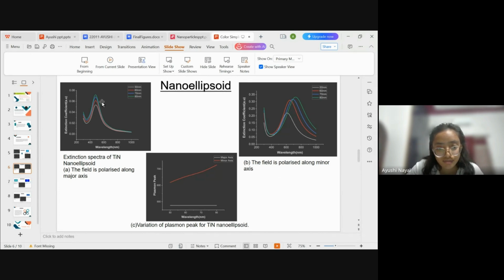The peaks in the graph show the wavelength where the nanoparticle strongly interacts with the light. The two graphs show the different orientations when the light is polarized along the major axis and the minor axis. The third graph is between variation of plasmon peak versus size. Plasmon peak shifts based on the shape and polarization direction of the nanoellipsoid. And this suggests that by modifying the structural parameters of the nanoellipsoid, one can achieve desired resonance.